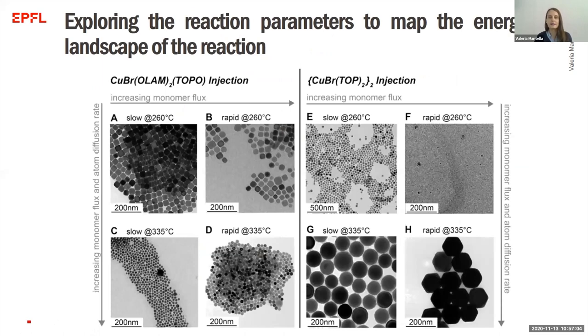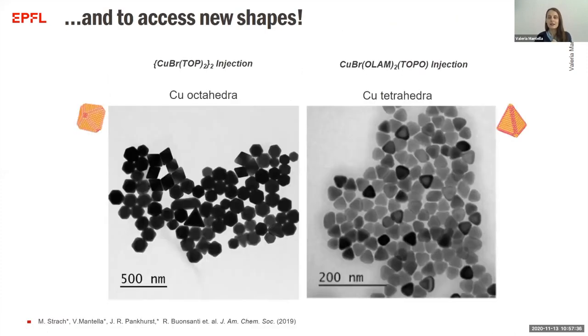And so having learned this, then we started to explore other ways to control this monomer flux. And in particular, what we did was to pre-synthesize these reaction intermediates and then inject them into the solvent using different modalities. And we expect a fast monomer flux from a rapid injection and a slow monomer flux from a dropwise injection for the same temperature. And so playing around with the monomer flux, we could further explore the energy landscape of the reaction and access other kinetic products such as octahedra or tetrahedra, where the latter ones were not synthesized before in the case of copper.